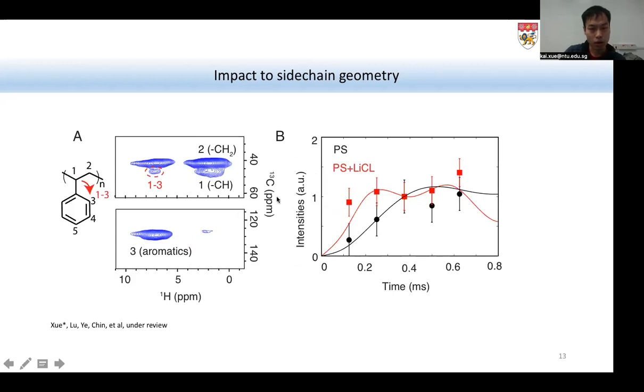This is the spectrum that I have for the polystyrene. I recoupled proton-proton dipolar couplings using RFDR and obtained this mixing peak from protons from the first site to the third site and from the third site here. In order to verify that the distance between the backbone and the sidechain is different, I measured the time-dependent RFDR curve for the polystyrene sample alone and for the polystyrene sample with the addition of lithium chloride, and observed these two different curves.